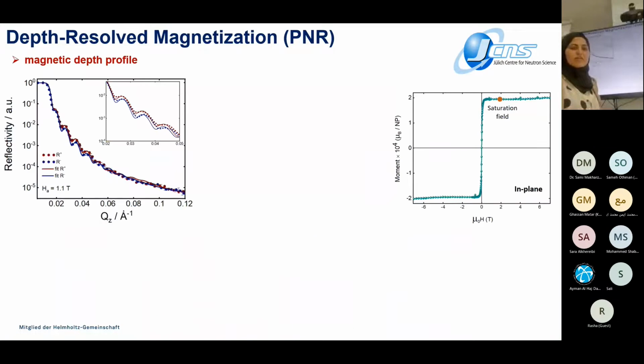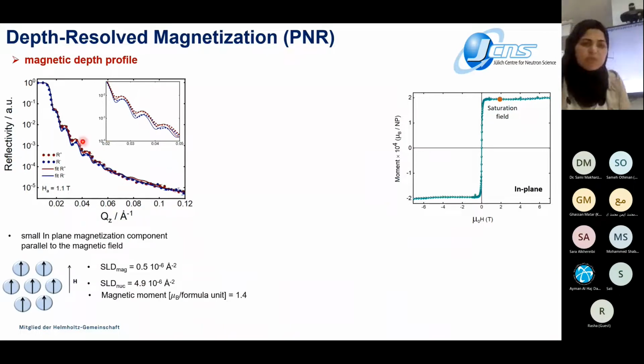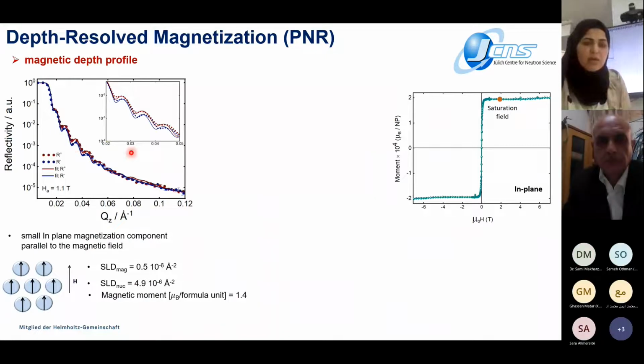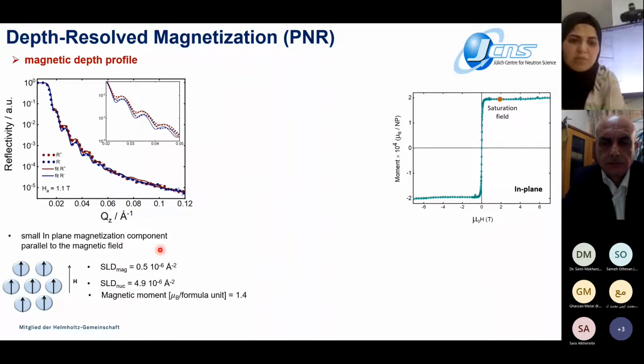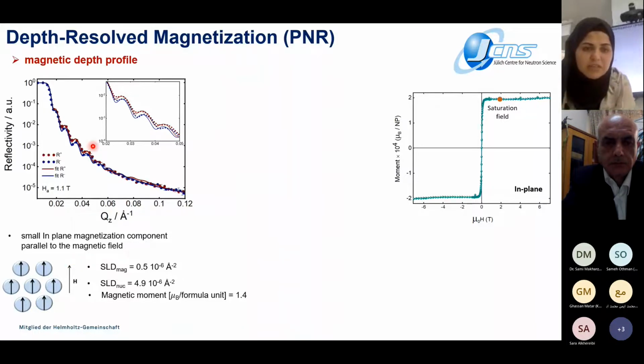depth profile. This measurement was performed at room temperature and two different fields, at saturation field around 1.1 Tesla, and we measured half polarized neutron. And with this, we can see there is a splitting between spin up and spin down, here the red and the blue curve, which is an indication of a small in-plane magnetization component parallel to the magnetic field. By fitting this data, we end up with a magnetic moment equal to 1.4 μB per formula unit, which is smaller than the bulk value, which is due to the frustration effect of the magnetic dipole interaction. And also we calculate this magnetic moment using the magnetic SLD and the nuclear SLD value.